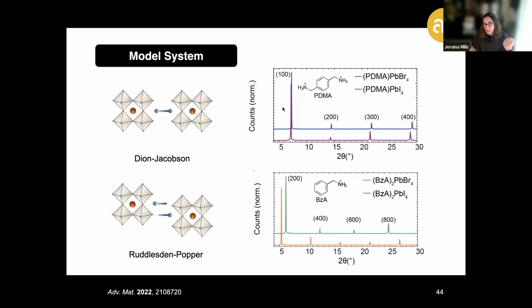Indicative of the formation of the layered structure, often preferentially organized parallel with respect to different substrates, in both of these cases showing also larger d-spacing for the Ruddlesden-Popper architectures as compared to the Dion-Jacobson ones, and the smaller spacing for the bromide-based systems as compared to the iodide ones, unlike in the surprisingly benzylammonium-based case where this trend is inverted, suggesting also a slightly different assembly in the bromide-based benzylammonium system within these materials.